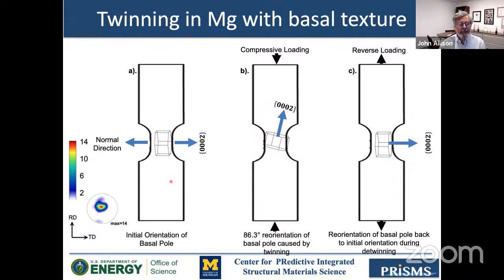Now here we've tried to depict what happens. If we're loading along this extrusion direction, the basal planes are oriented orthogonal to that extrusion direction. If we load it in compression, then we're actually getting a Poisson's effect that loads the planes that induce twinning. And so we get twinning that flips basically 86.3 degrees within a given grain. I'll show more micrographs of that in a bit. So these twin planes orient at roughly 90 degrees. And then if we load in tension, we reverse that. Then these twins detwin and flip back.